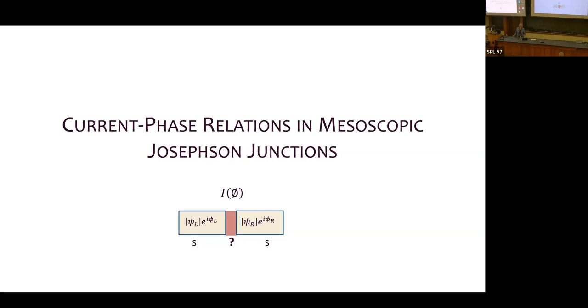And if there's a different phase between these two blocks of superconductor, you get some current flowing between them, and the current is a function of the phase. So the current as a function of the phase is called the current phase relation. And in the classic simple example that you learned about first or that you read about in Wikipedia, actually the Wikipedia article on macroscopic quantum phenomena says, we assert without proof that the current phase relation is I equals the critical current times the sine of the phase between them. Okay, so that's called a sinusoidal current phase relation.